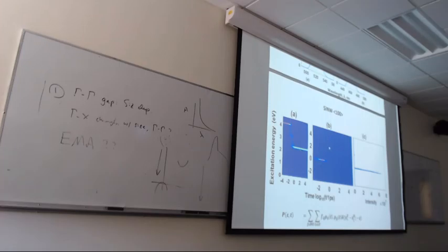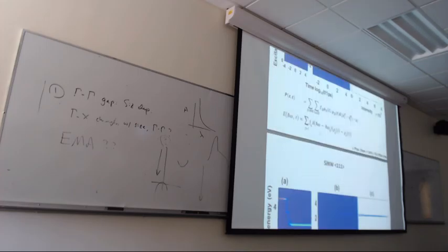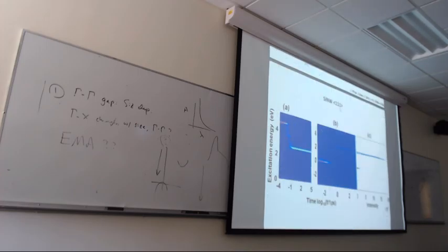So this is for the silicon nanowire along the 001 crystallographic direction, and the next one is for the silicon nanowire along the 111 crystallographic direction. We consider the photoexcitation, exactly similar to silicon 100, of an electron from HOMO minus 14 to LUMO plus 14 with energy around 4.5 electron volts.